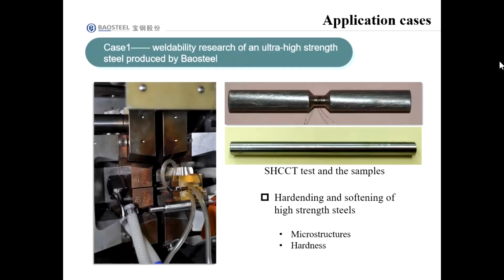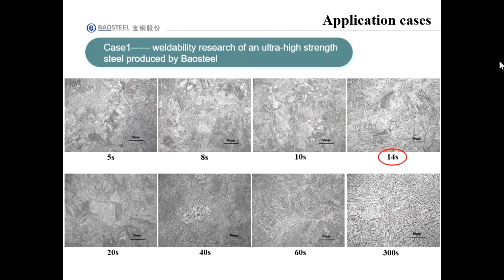The first one is used when the cooling rate is very fast. Microstructures of simulated coarse-grained HAZ are shown in this slide. The thermal cycles are that the peak temperature is 1350 centigrade and the cooling time t8/5 is different, from 5 seconds to 300 seconds. So the microstructure is different. We can see how the microstructure evolves with different cooling times.